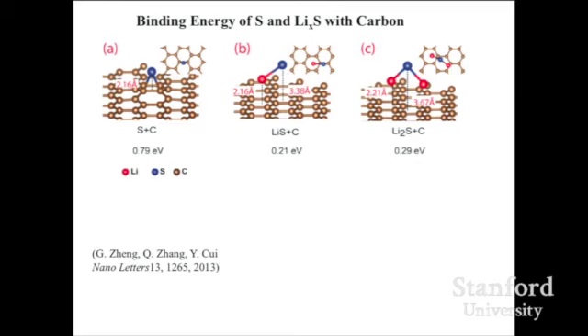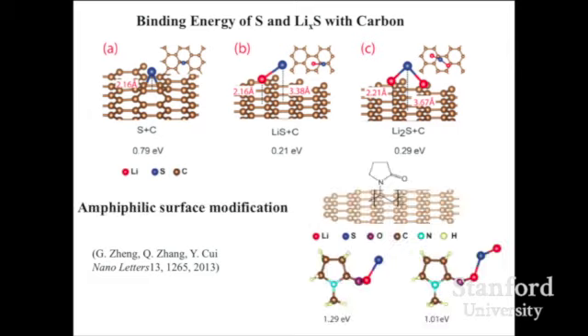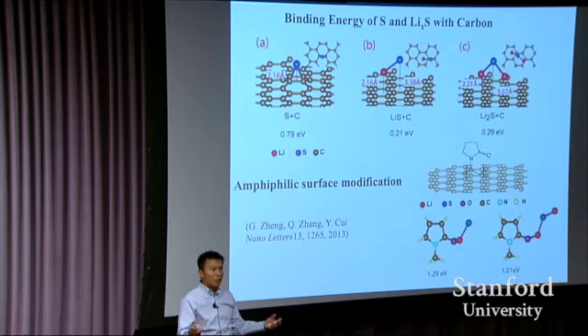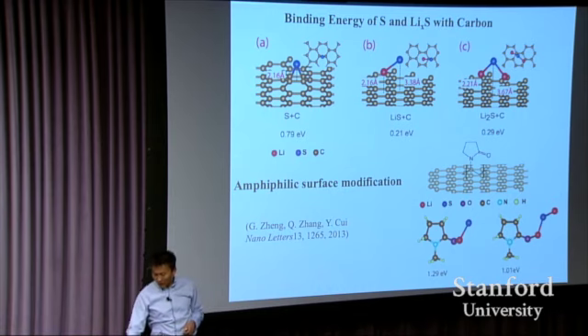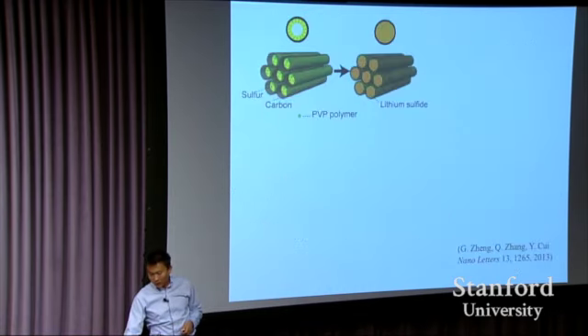So why don't we do this then? We can actually confirm this: sulfur likes carbon, bonding energy is high through ab initio simulation. But lithium sulfide, they don't really like it at all. This is confirmed. Then we said, why don't we put in a bifunctional polymer right there? For example, PVP. It's a polymer having a hydrophobic chain with this polar group right here. This guy must like lithium sulfide. They're all polar. And the surface will like sulfur. So you have both engineered, co-located together, beautiful things in nanotechnology. That's what you can do. This really solved the problem.